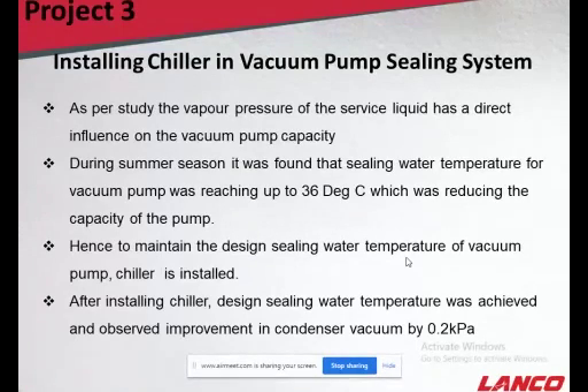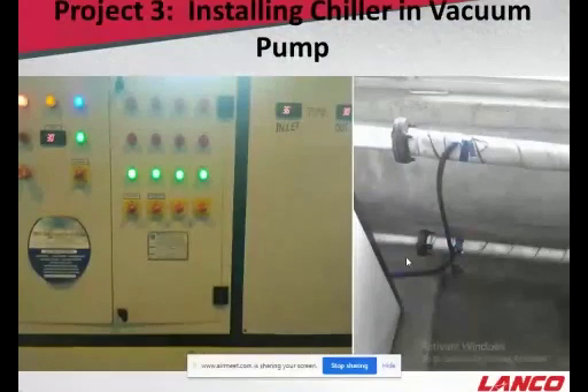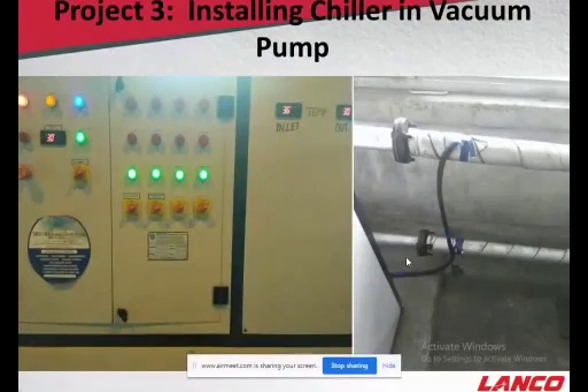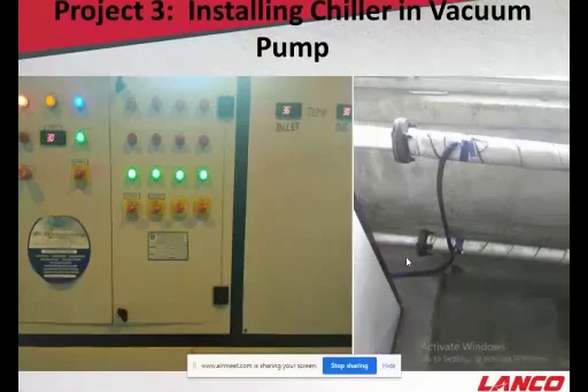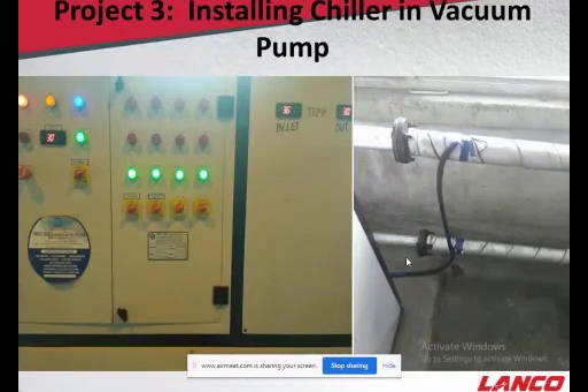Hence, to maintain the design water temperature of this vacuum pump, a chiller was installed. This chiller was designed for the capacity of the sealing water flow, and the temperature was achieved as per the OEM temperature. And this impact was seen as a vacuum improvement of 0.2 kPa. If you see the chiller panel, the inlet temperature was 36 and it was maintaining a 30-degree temperature, just below the design value of 32, to compensate for this.